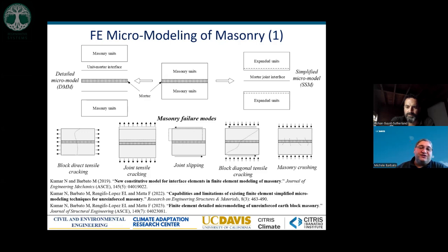Now, this model fundamentally assumes that everything that is breaking is happening in the interface, which is a reasonable assumption for ordinary masonry, where the blocks are typically very strong and the mortar is weaker. But for earthen construction, the mortar is very similar. It's done with the same material as the blocks. So this assumption that allows the use of a simplified micromodel simply is not satisfied. And so we came up with a detailed micromodel where we actually model explicitly also the layer of mortar.